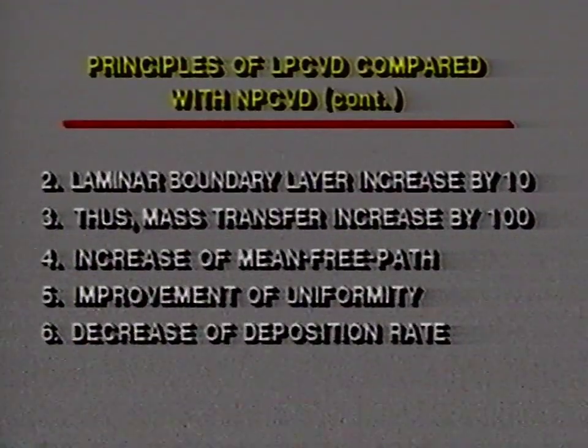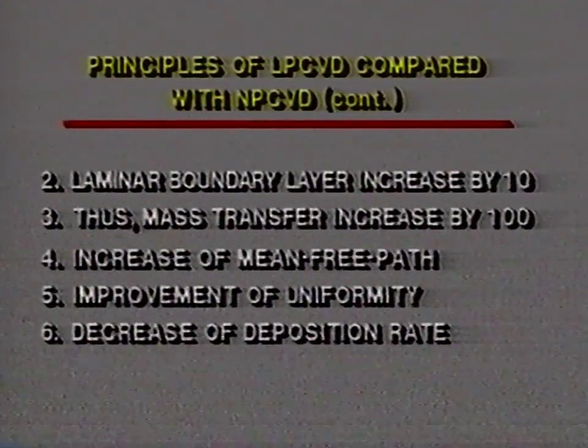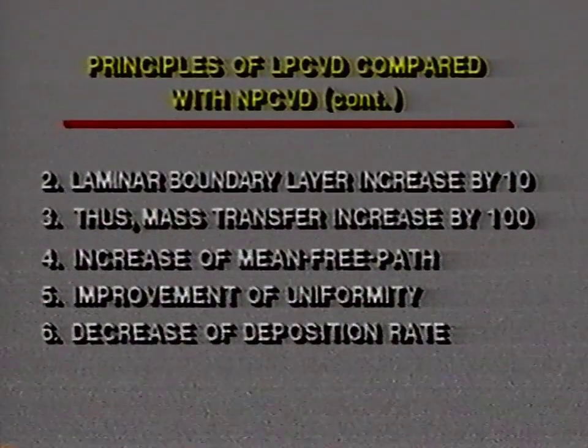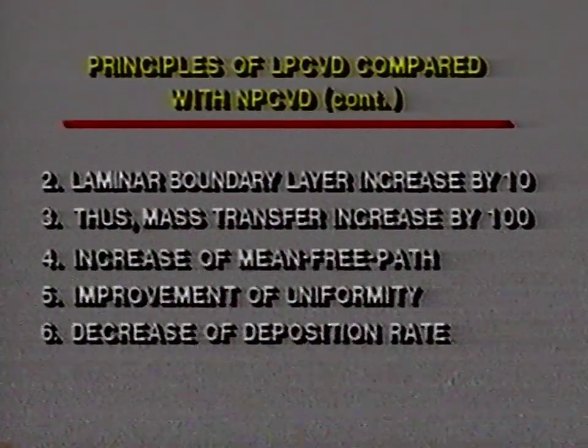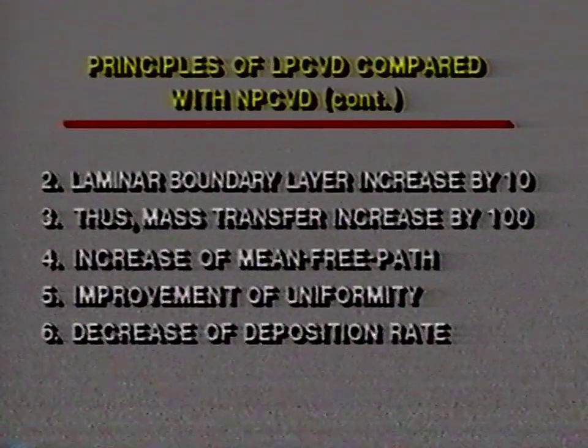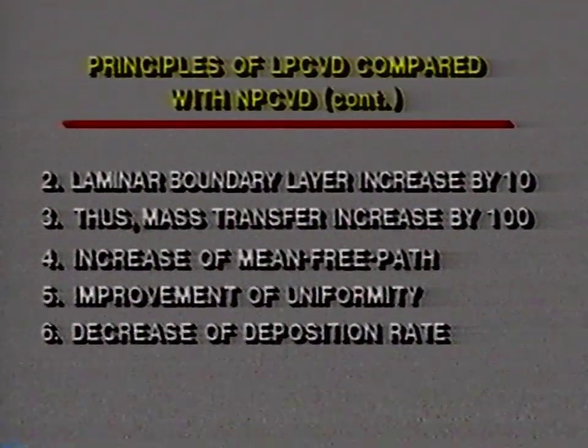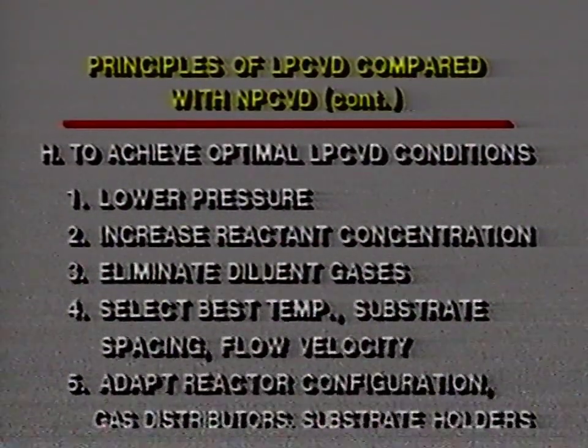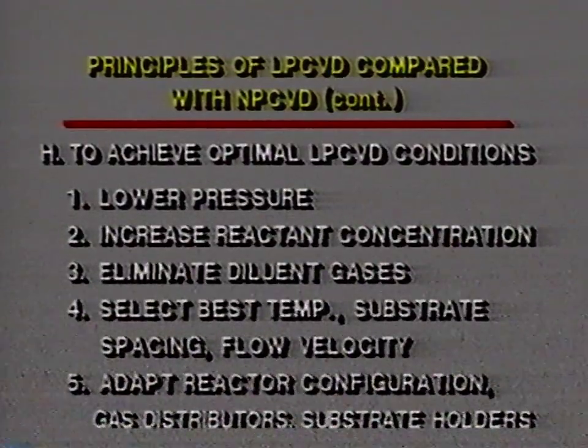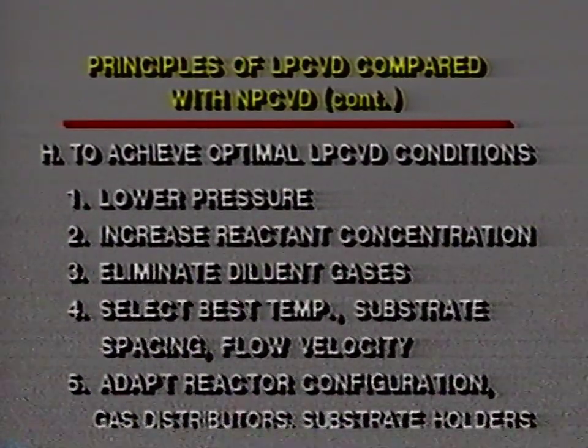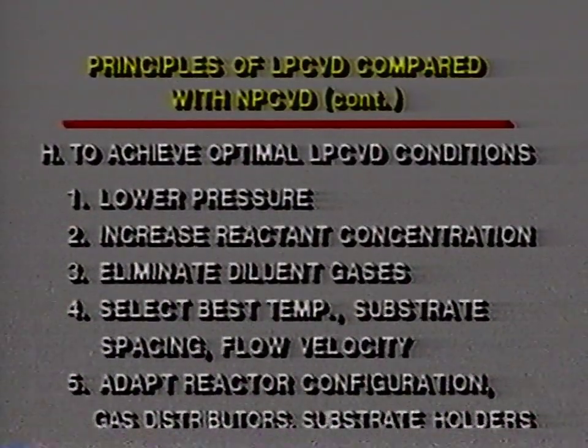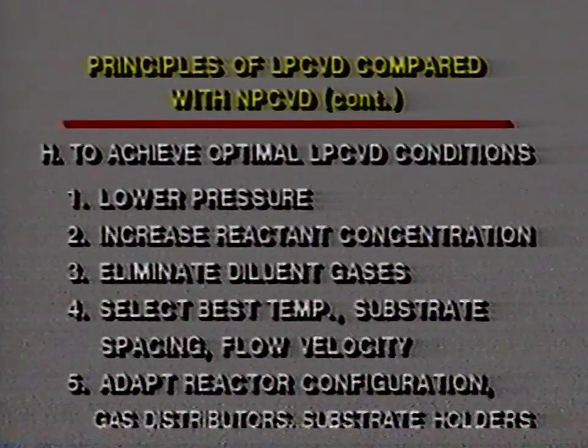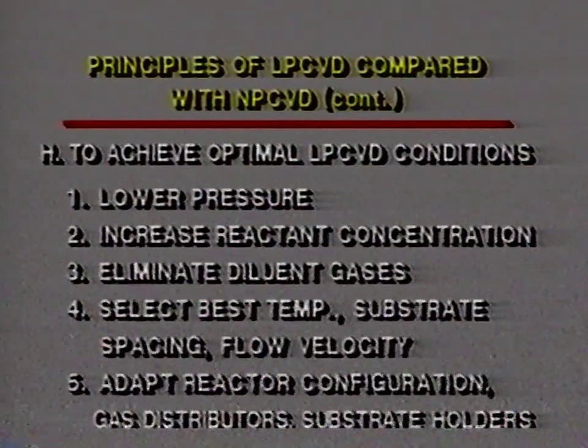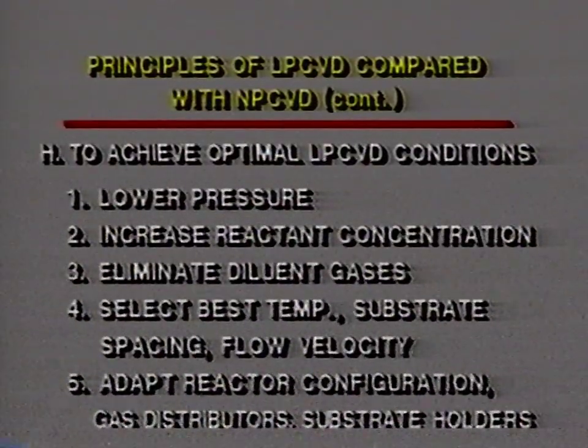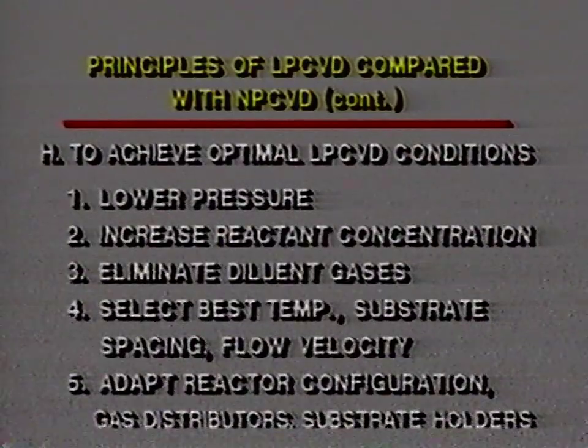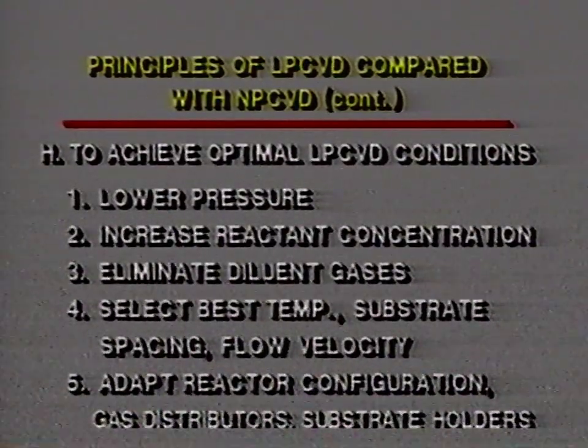Another negative aspect, of course, is that the deposition rate is decreased simply because we have less material available at low pressures than you would have under atmospheric conditions. Now, to achieve optimal LPCVD conditions in practice, one would have to do a number of things besides lowering the pressure. Increase the reactant concentration, to get a high partial pressure of the reactant itself, and eliminate the diluent gases to achieve this, which is, of course, economically a desirable thing.